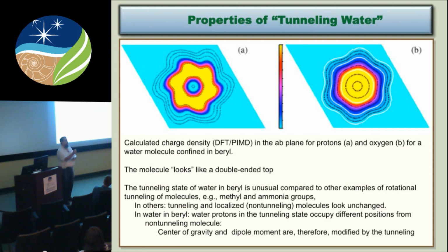So what we've shown then is what's essentially a new state of water. Water in these conditions looks like a double-ended top on average, and not from vibrational motions, but from tunneling motions. So we'll have something where the hydrogens are equally distributed on average around the top and bottom of the water. There may be actually a little bit of motion of the oxygen. And so what you've done is change the symmetry of the thing.